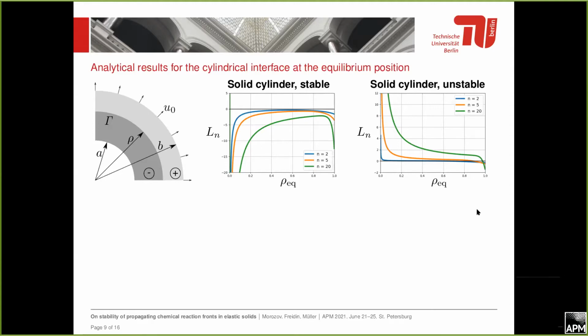And the opposite we see when we consider an unstable configuration. We see that some effects on the edge appear, but those are limiting case effects, which may be due to the problem that if we have a very thin layer of new material and we want it to be stable, it's a bit different problem. So the interface starts to forget that it is a cylinder. With a very thin external layer of new material, we may even switch to the planar interface solution. But for, for example, 0.6 and lower equilibrium radii, we see that for an unstable set of material parameters, all the values are positive, and we expect this configuration to be unstable.